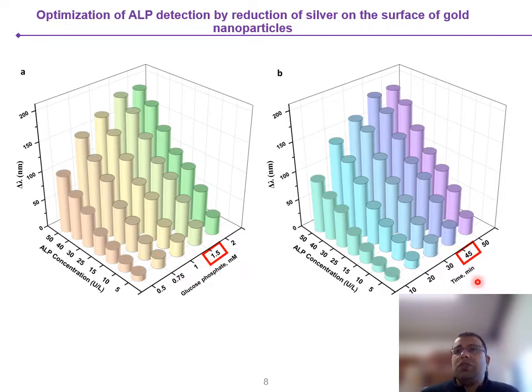And also for incubation time, we tested different times with different concentrations of ALP. We found that with increasing the time, the shift in wavelengths increases until it reaches 45 minutes. So this is the optimum time for this experiment.